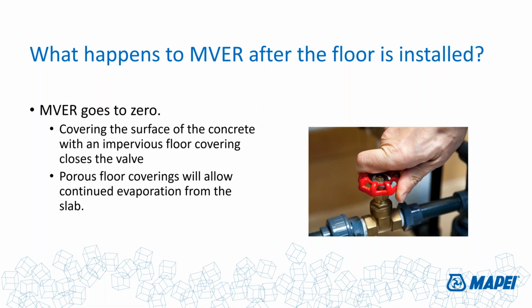Now, what's also important to note about the moisture vapor emission rate information is that once you cover it with an impervious moisture material, whether that be an epoxy membrane, whether that be a vinyl sheet flooring, something that's non-breathable, or even tile, resilient tile products for the most part, once you start covering it with an impervious moisture vapor barrier or impervious floor covering material, you basically turn off the valve on the evaporation rate. That should be quite simple to you. And at that point, the MVER becomes irrelevant at some point. It no longer has an opportunity to evaporate into the atmosphere.